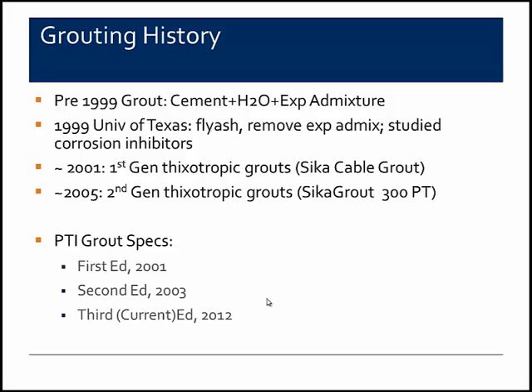A 1999 study at the University of Texas, funded by Texas Department of Transportation, first of all, concluded that the expanding admixture didn't work very well at all. It did not expand as anticipated to fill voids, and so there were significant voids left behind. They also studied the use of fly ash for those grouts. They studied some corrosion inhibitors available at the time, and basically they concluded that the cement and water grout that had been used up to that time was very poor as a corrosion mitigation method. It did not perform well at all.